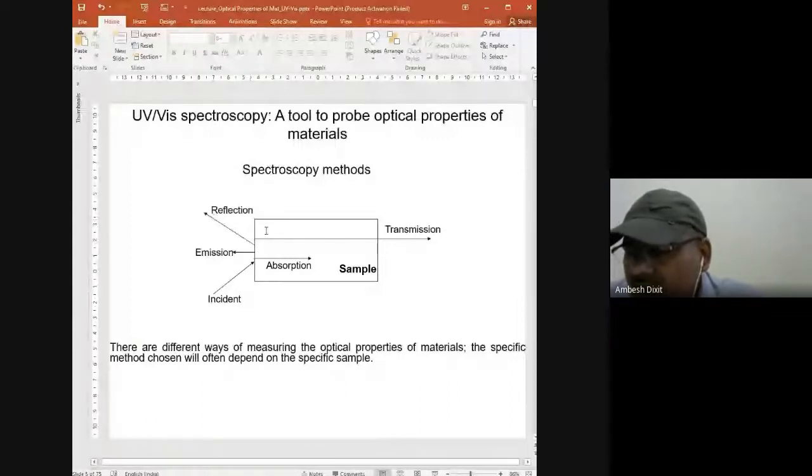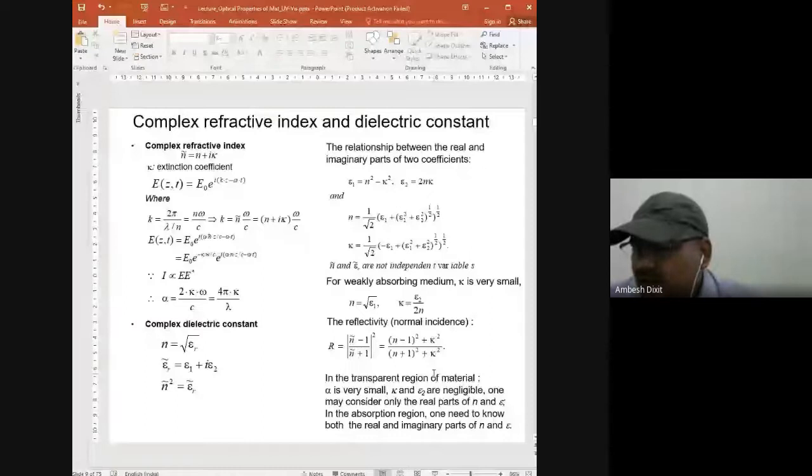Right? Typically those who have done some fitting know this is the relation. What they can do is try to fit with different n and k as a function of lambda, and then see when the values of n and k for those wavelengths will satisfy this measured R, and you can back it out and then get it.